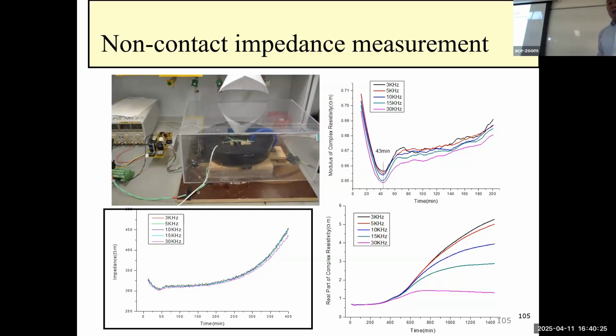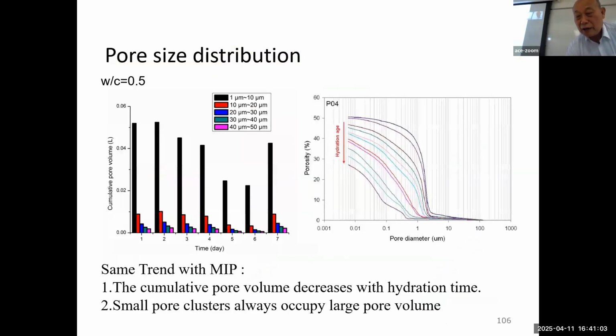My fourth student used this technique and extended the resistivity measurement to multiple frequencies, which is called impedance. The impedance needs multiple frequencies, and you measure both the real and the imaginary part. At different frequencies, they have the same point at the lowest, which is a very good indication. Later on, he used this to distinguish the pore size inside concrete.